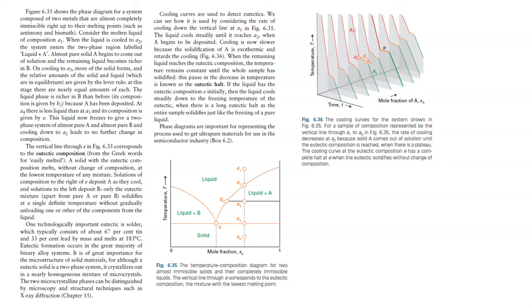Cooling curves are used to detect eutectics. We can see how it is used by considering the rate of cooling down the vertical line at A1 in figure 635. The liquid cools steadily until it reaches A2. Then A begins to be deposited. Cooling is now slower because the solidification of A is exothermic and retards the cooling, which is what we're seeing in figure 636. When the remaining liquid reaches the eutectic composition, the temperature remains constant until the whole sample has solidified. This pause in the decrease in temperature is known as the eutectic halt.